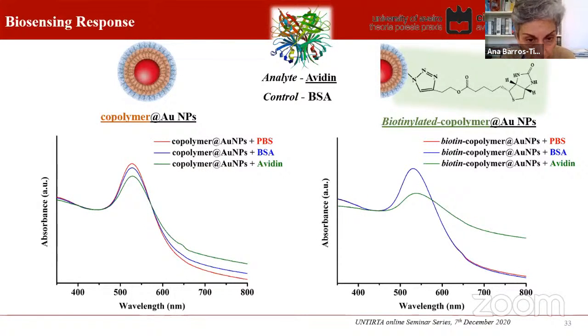These biotinylated gold nanoparticles were compared with the original gold nanoparticles functionalized just with the copolymer, in the presence of avidin. For control, we used another protein, BSA, and also as a control or a blank, we used physiological serum, so that we knew that whatever result we were going to get was associated exclusively with the analyte, in this case, avidin.